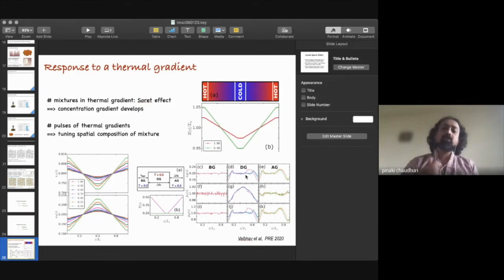Now if I switch off my thermal gradient, then again I have a flat temperature profile, and if I'm at a temperature below the glass transition temperature, then essentially all my dynamics is stopped and it is an arrested state. So in this way I can generate concentration profiles inside the system, and depending upon the requirement, I can tune my thermal gradient such that I have the preferred concentration profiles. This way I can alter the composition of the material across the spatial scale by applying this kind of thermal gradients. And this is something that is actually observed.